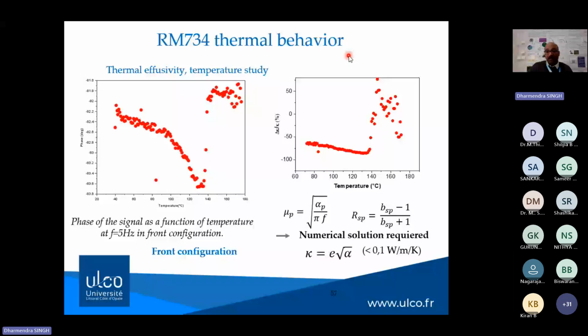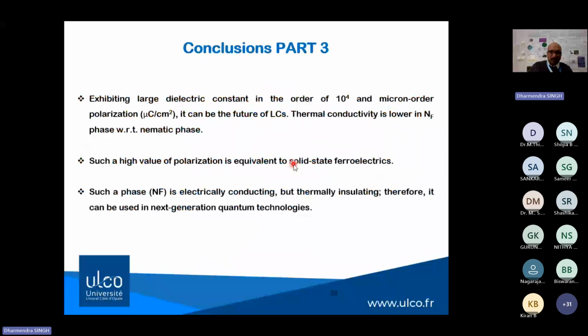Here is the conclusion of my third part, which is the last part. Exhibiting a large dielectric constant in the order of 10 to the 4 and microcoulomb-order polarization, it can be the future of liquid crystals, and also of organic semiconducting materials. Thermal conductivity is lower in the NF phase with respect to the nematic phase, and such a high value of polarization is equivalent to solid-state ferroelectrics. Because it is electrically conducting and thermally insulating, it can be used in next generation quantum technologies.